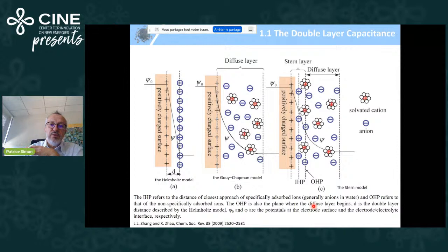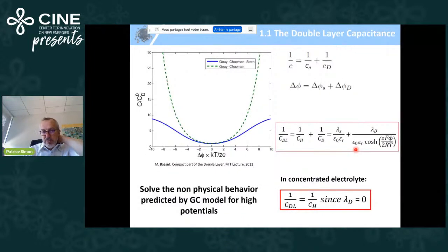And then finally, to unify these two models, Stern considered a first inner Helmholtz capacitance layer, together with a diffuse layer, to depict the ion adsorption in the electrochemical double layer. If you use this Gouy-Chapman-Stern model, you see a finite capacitance at high potential, you still preserve the hyperbolic shape, and you fit the experimental plots much better. So you can see this double layer capacitance as two capacitances in series, one Helmholtz capacitance and the second Gouy-Chapman.